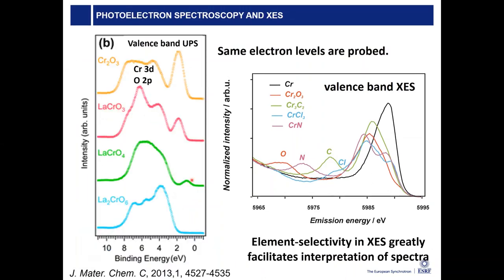And you can compare this, by the way, the valence to core X-ray emission lines, they reach formally the same electronic final states as valence band UPS I showed at the beginning, right? So you can compare for chromium oxide. So this shape here, you would have to compare the chromium oxide here, which is the red line there. So only this line there. So in principle, it probes the same part of your electronic structure, but different selection rules, different energy resolutions, so the spectra look different.